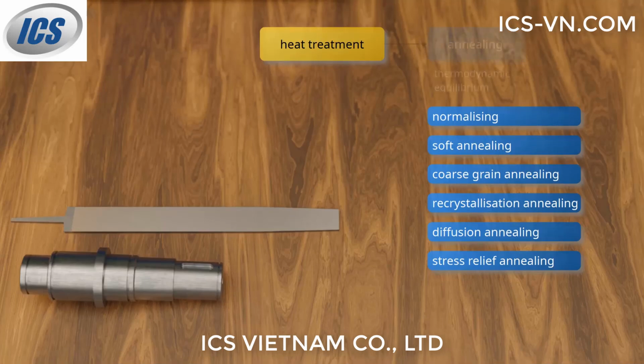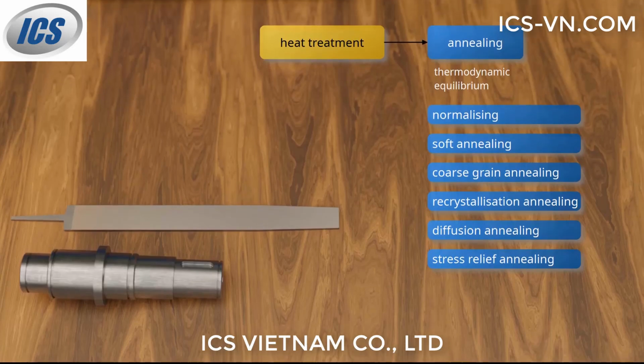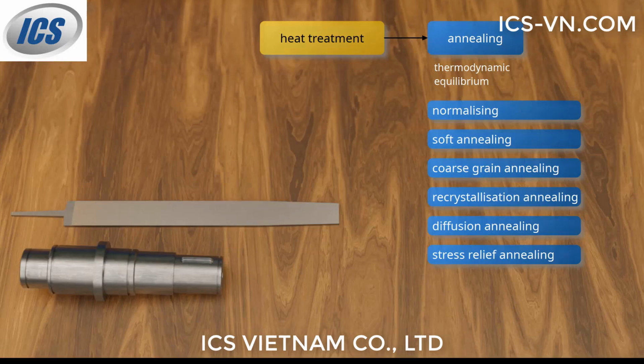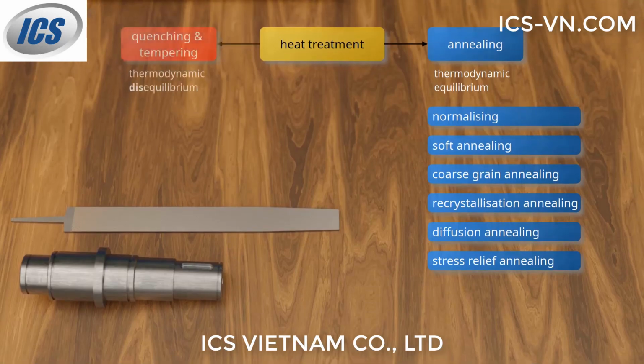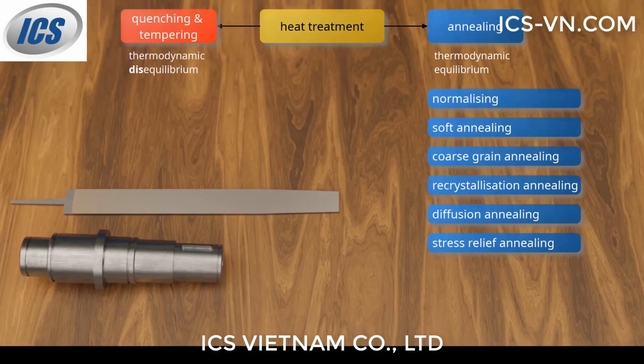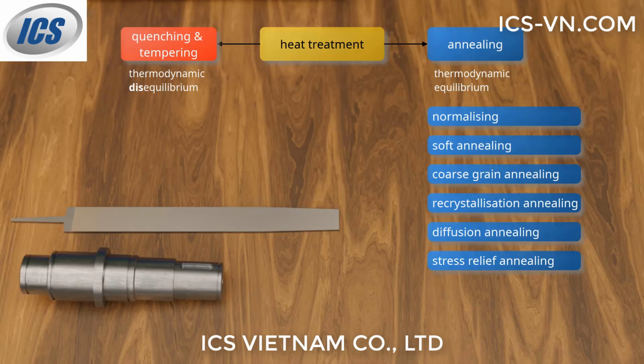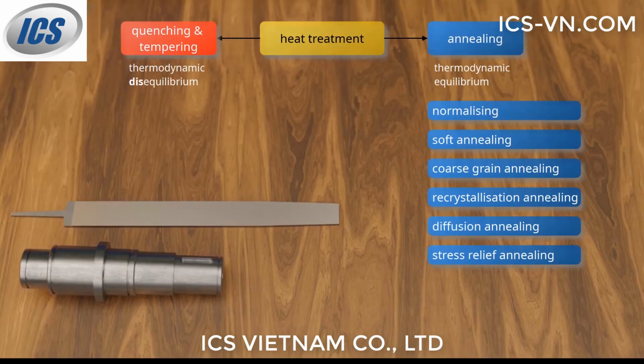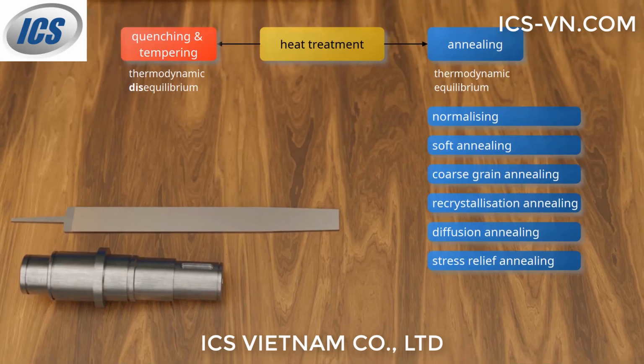Whereas in these so-called annealing processes the driving force for the respective microstructural change is always the achievement of a lower energy state, that is, the establishment of a thermodynamic equilibrium, quenching and tempering involves a thermodynamic state of disequilibrium of the microstructure. The establishment of thermodynamic equilibrium is specifically prevented by rapid cooling. Because of these fundamental differences, quenching and tempering are usually listed separately from the aforementioned annealing processes.